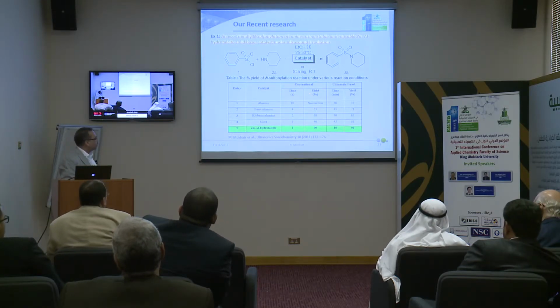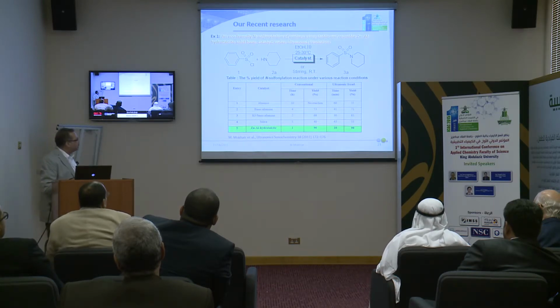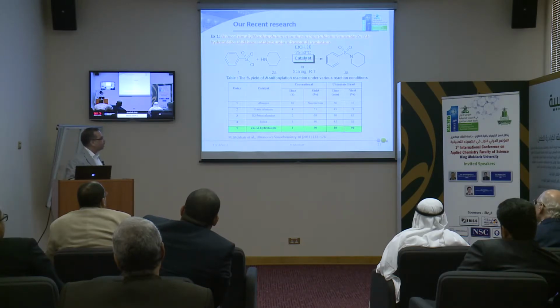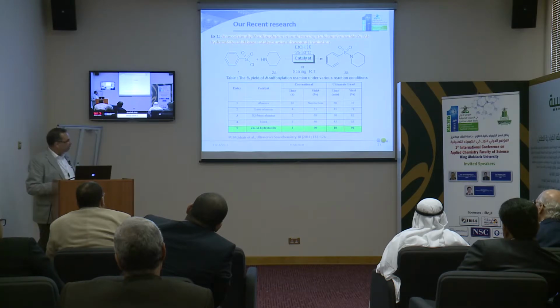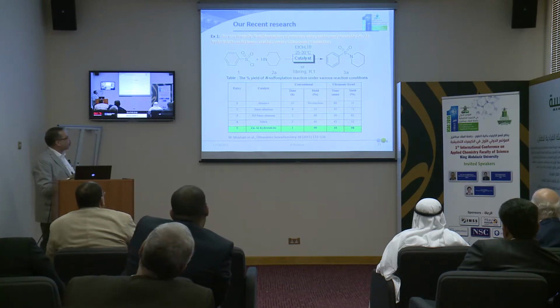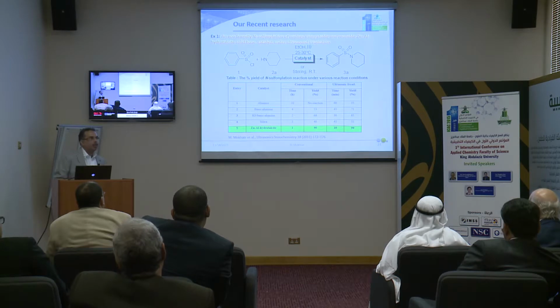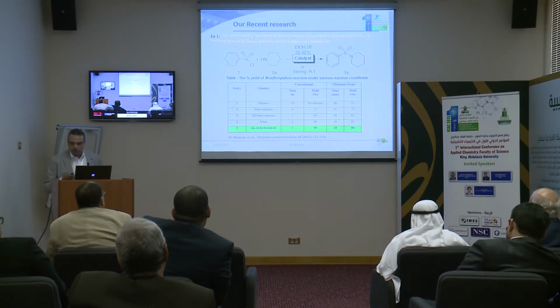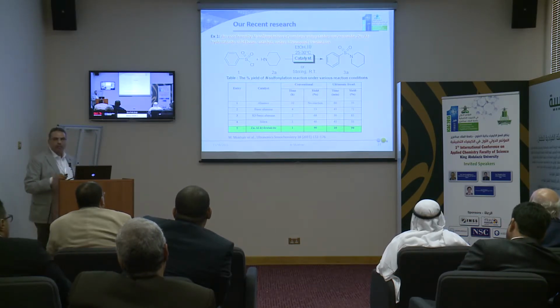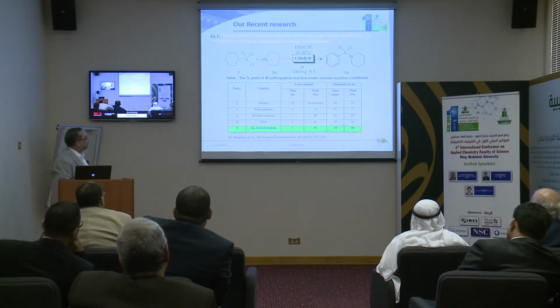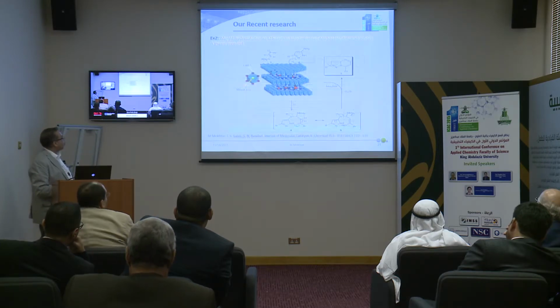We found that in comparison for the conventional method, we have a 90% yield. The time was 1 hour, but using ultrasound irradiation, the time is reduced to 10 minutes and the percent yield is increased much more. So this means combining layered double hydroxide, which is environmentally benign, with the tool itself, which is ultrasonic irradiation, gives promotion to obtaining such important materials for fine chemicals.